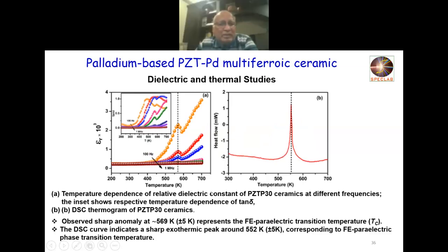In this material, we did temperature dependence of the dielectric constant, and we found some kink in this region, which is indicative of a ferroelectric phase transition, since at different frequency it is occurring at the same place. We also confirm this transition with the heat flow, and we can see a sharp anomaly at that particular temperature. So in other words, we can clearly say that in this material we have a phase transition around 560 degrees.